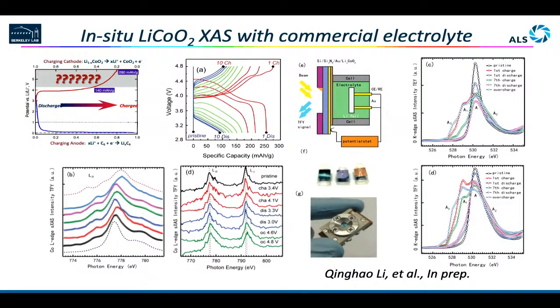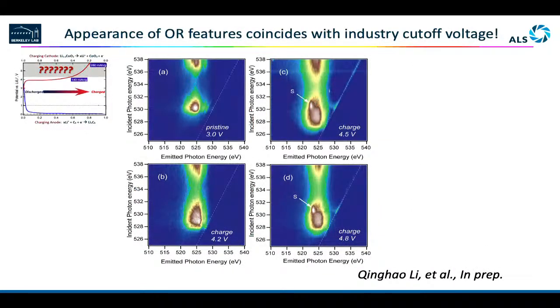I just want to mention one very quick thing, because I have been talking about lithium cobalt oxide, so I don't want to leave this as a whole. This is one of the topics we have been working on a lot with Tom Devereux at Stanford. We really try to solve this issue of what kind of oxygen redox is truly useful to have: reversible, and also not a kinetic or thermodynamic issue on the cycling, on the voltage when you cycle for extended cycles.